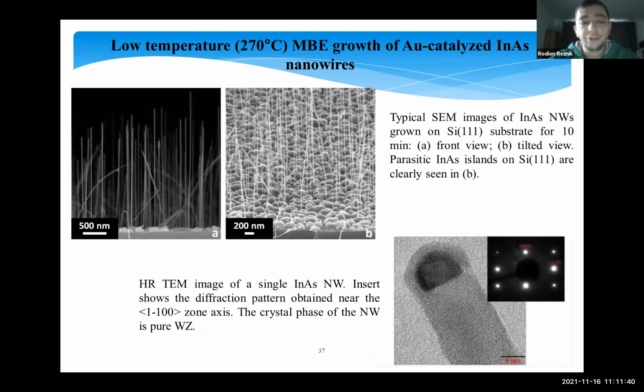Also, again, low temperature is important for silicon technology, and we have grown low temperature indium arsenide nanowires at only 270 degrees via the vapor-solid mechanism, because the nanoparticle at this growth temperature is not liquid, it's solid. In this case, we also had a higher growth rate of nanowires compared with the vapor-liquid-solid mechanism, which was described by Vladimir Dubrovsky and Alexander Koryakin. It is important to know again that we have a pure wurtzite structure of indium arsenide nanowires.